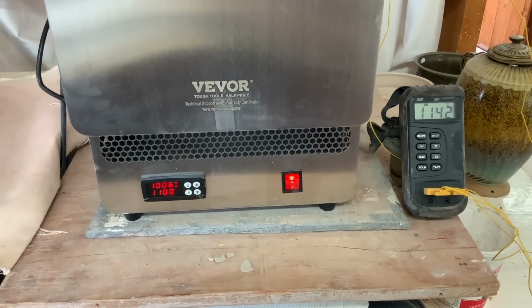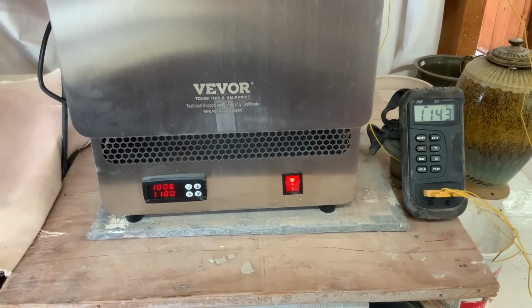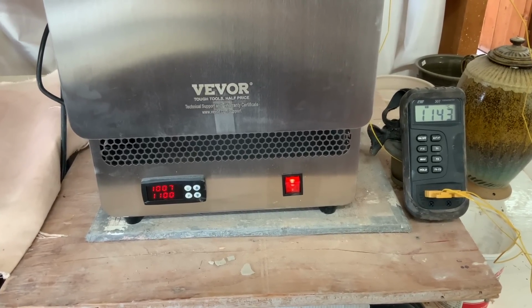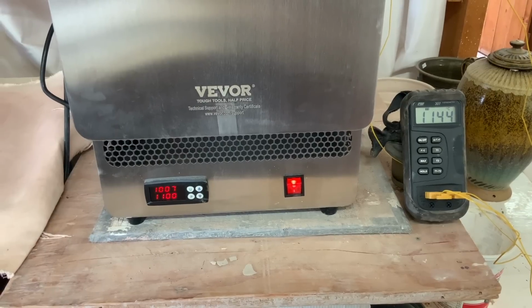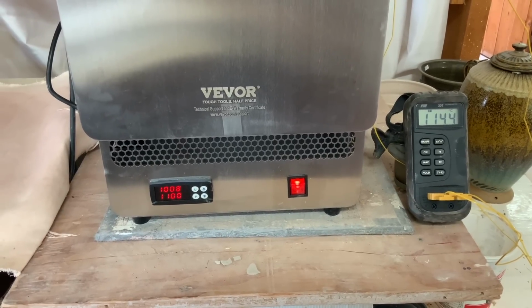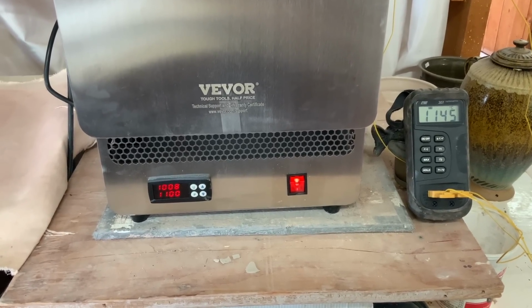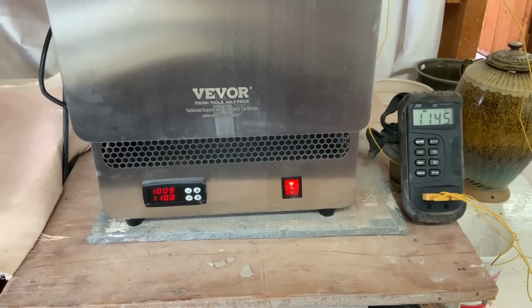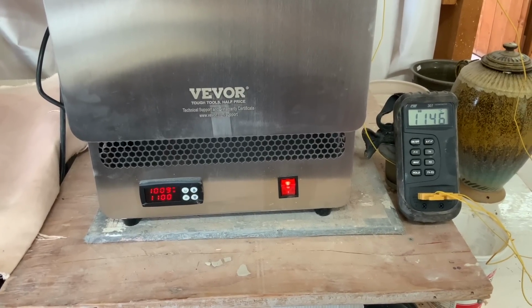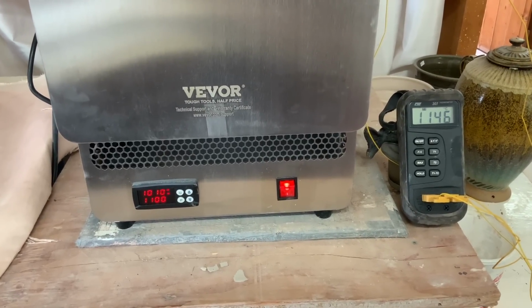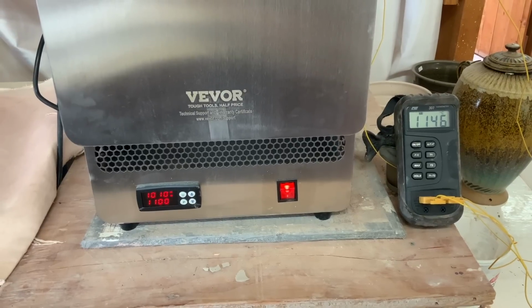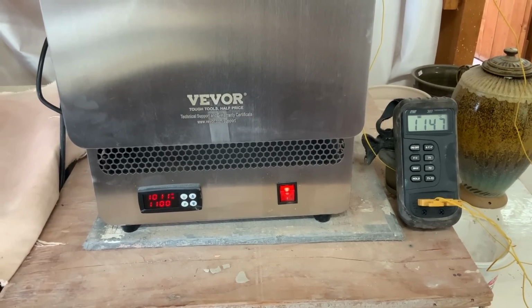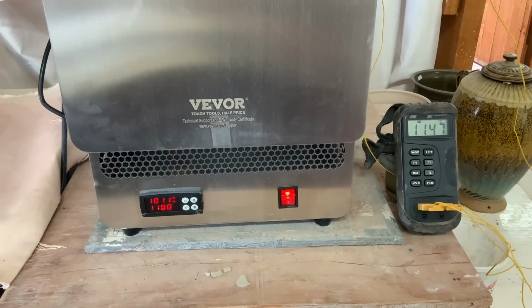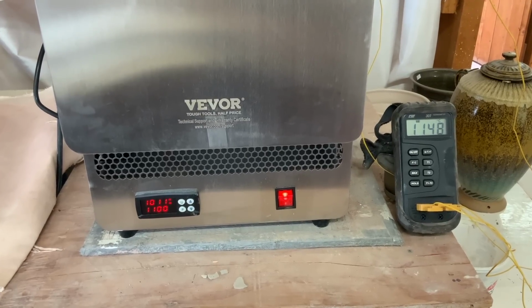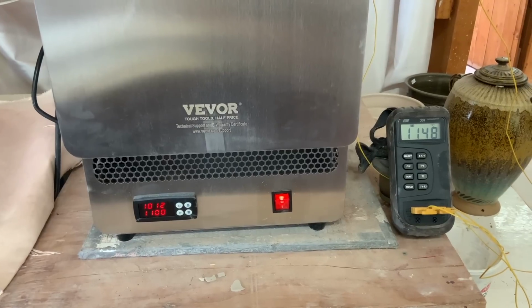Okay, we're already at Bisque temperature as far as that kiln is concerned, but we've already discovered that Bisque, which is 1025, actually is reached around 850, 900. So the temperature in the kiln is 1009 on their thermometer, and on mine it's 1146. So we are less than 150 degrees apart now. So it looks to me like as it increases in temperature, it actually is evening out.